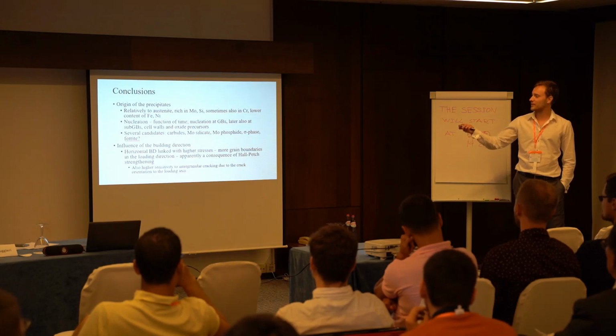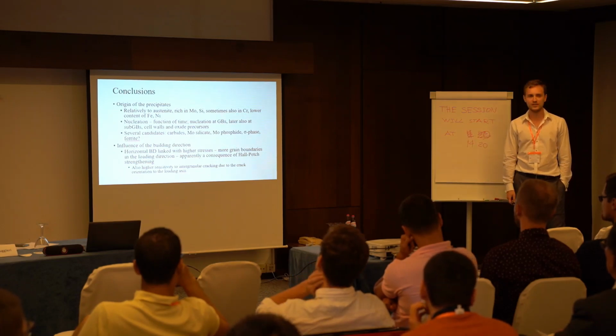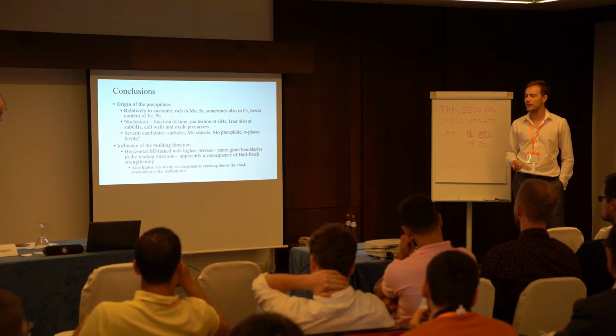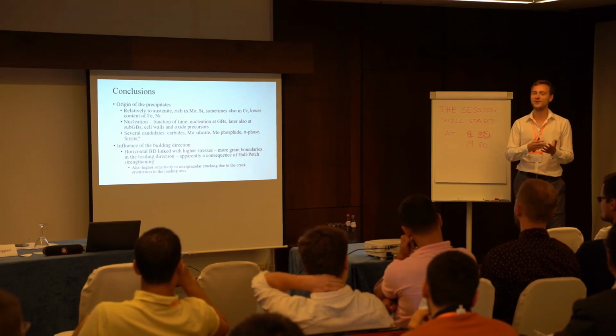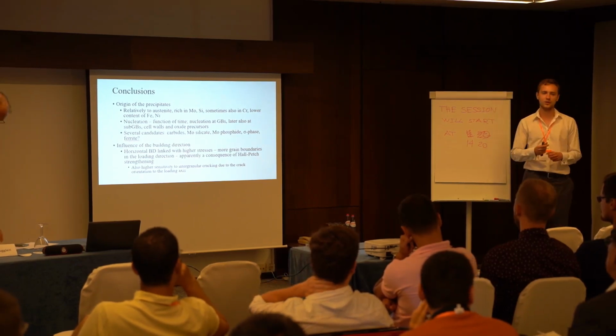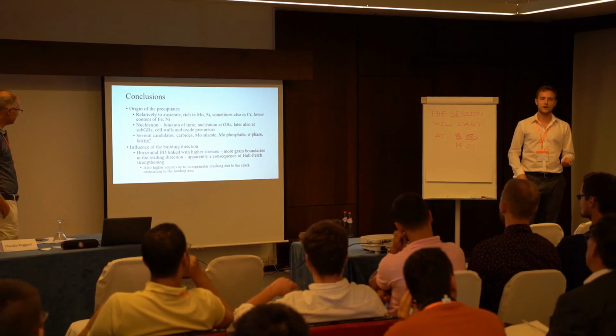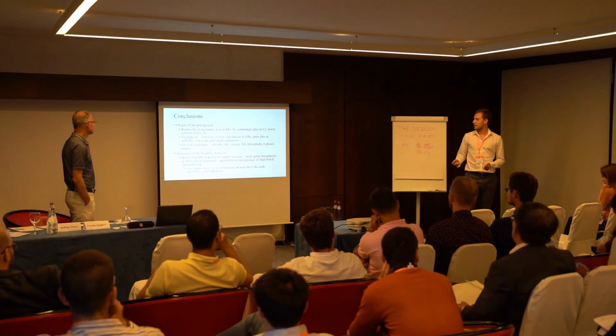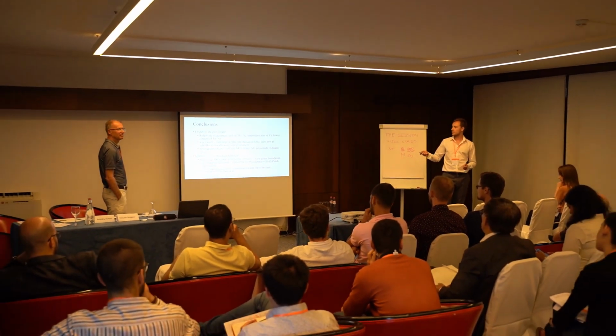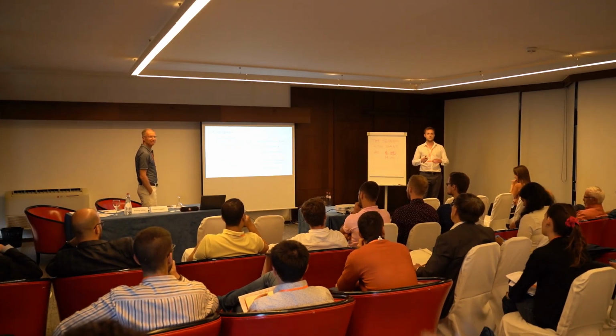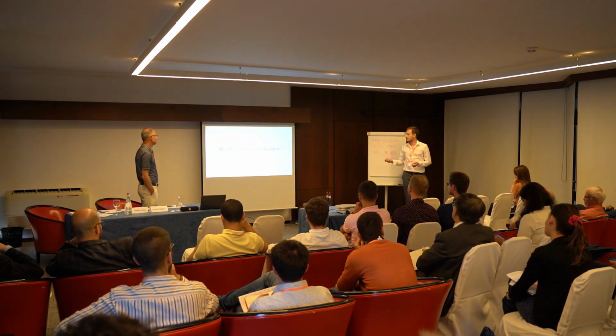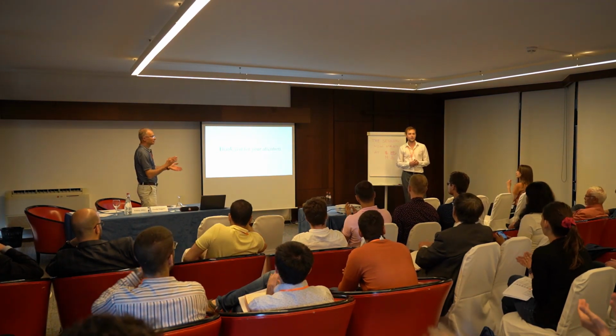Regarding the influence of the building direction, can I just finish the sentence? We saw that the horizontal building direction was linked with higher stresses, which is apparently caused by a not huge but higher amount of grain boundaries in the loading direction, which is the cause of higher grain boundary strengthening. We also saw higher sensitivity to intergranular cracking, which is quite obvious since if we have cracks like this and we load it like this, it's easier to open, right? So that's it. Thank you for your attention, and if you've got any questions.